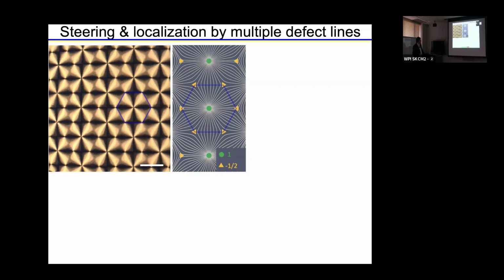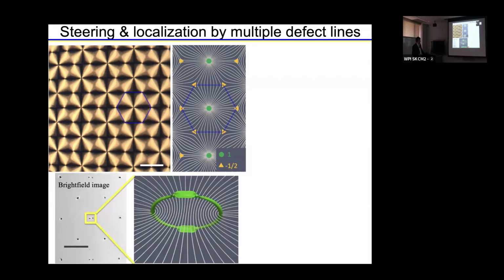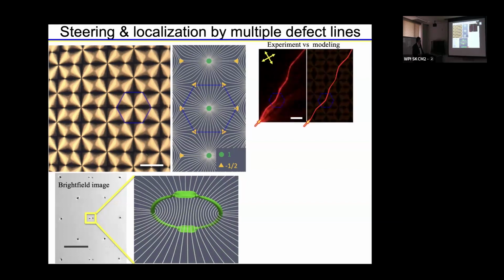So in here, you can see we made crystals out of half integer -1/2 and +1, where for the overall crystal, it's important to have the neutral overall charge of optical vortices. And what's interesting is that when we pattern an integer strength vortex, as these lines in this three-dimensional bulk tend to split into two half integer ones that correspond to these dark spots in here. And the reason is because the free energy corresponding to these vortices scales quadratically with the winding number. So therefore, an integer strength winding number vortex is replaced by two half integer ones because they cost twice less energy.